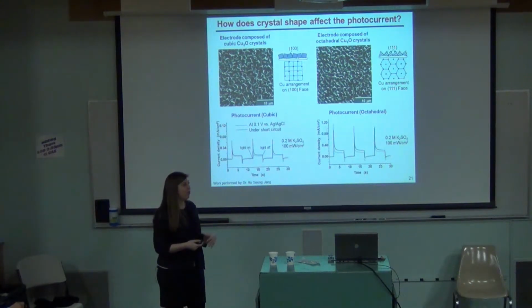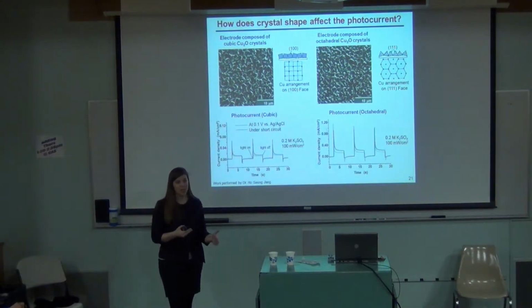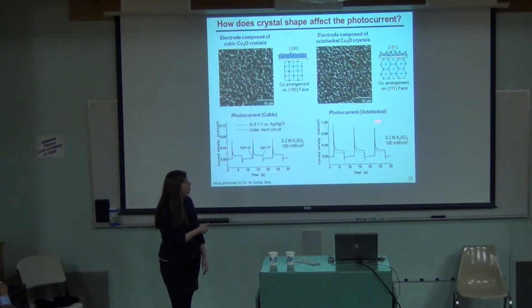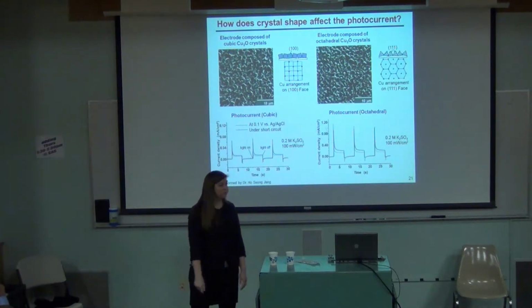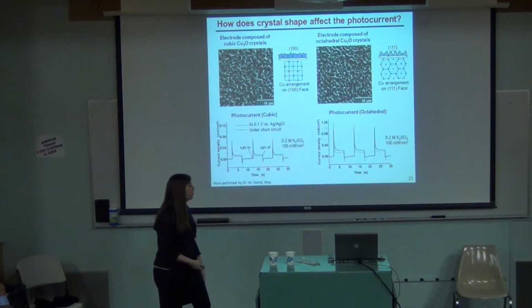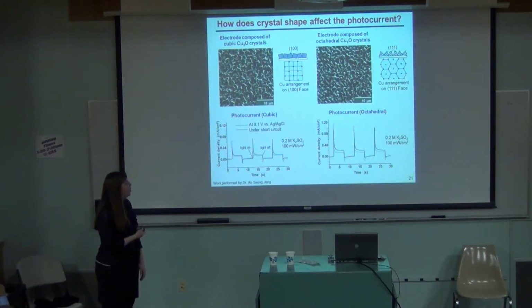So people have not really gotten a blank semiconductor to be any better than about 1% to 2% efficient, and then they just add all sorts of other catalysts and other things on top of it to get to about 12% efficient. So if we could get this from 0.2 to 1 up here, if it didn't die out, if it stayed up here, then that would be a pretty good material for a photovoltaic device or for electrochemical cells. And all we did here is change the shape. So that's pretty cool. And I care about why.